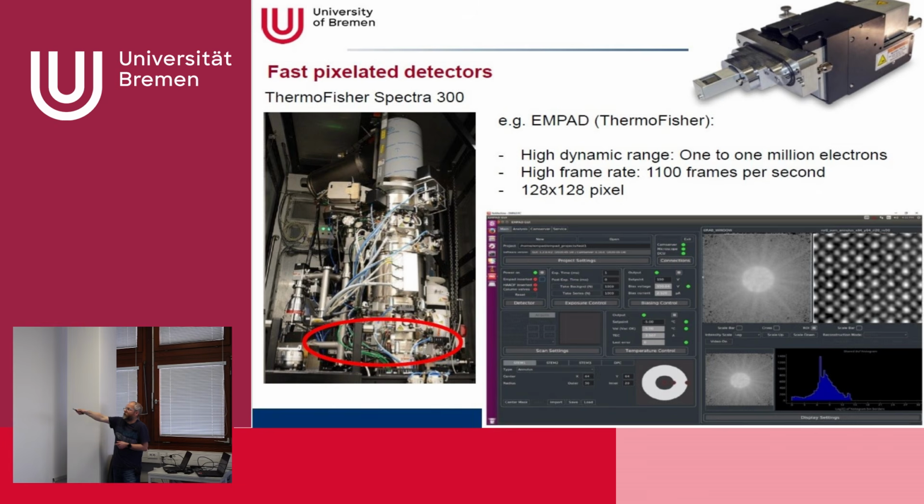And then we record, of course, the diffraction patterns, and then basically from this diffraction pattern we could later in the post-processing select maybe the high angle annular dark field range, or we could segment this inner area and measure the deflection of the beam here. So for measuring the electric fields in the specimen.